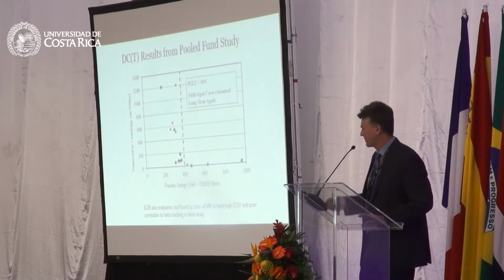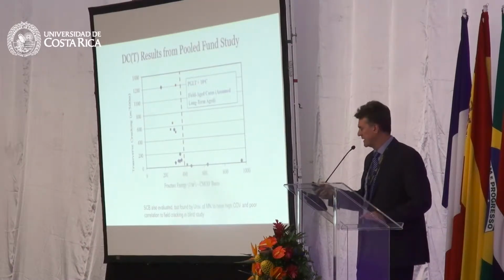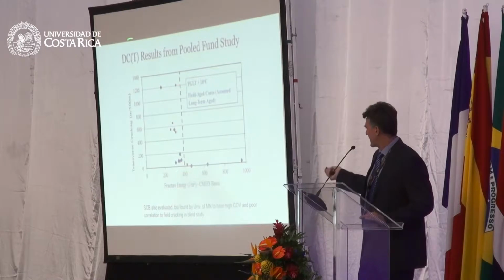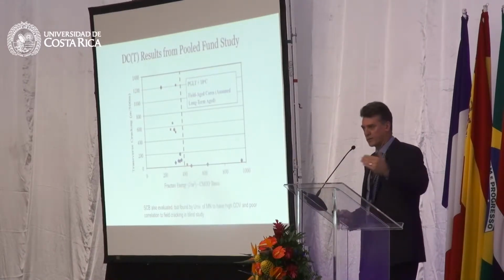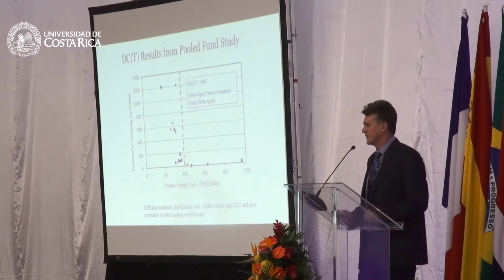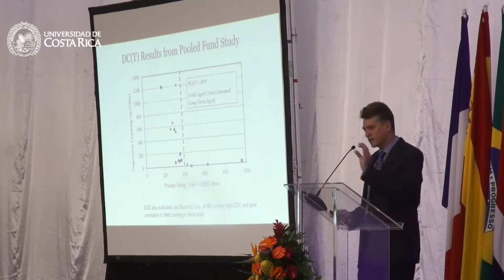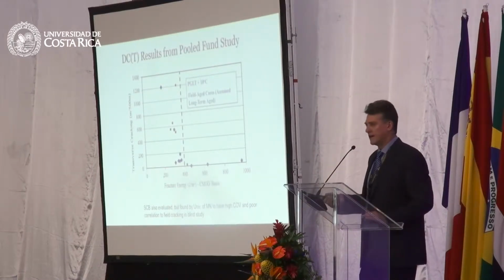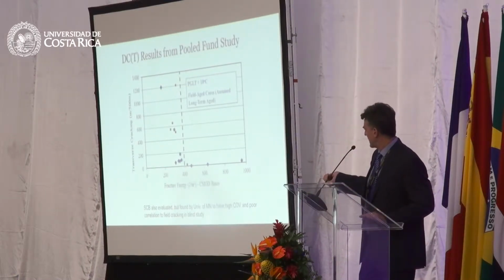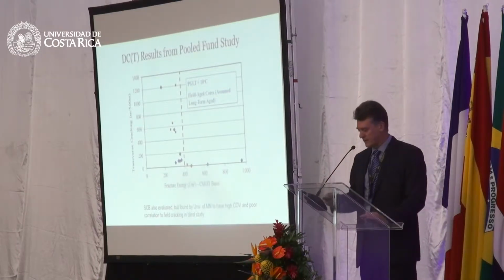We've done many, many more mixtures since this original study, but we definitely saw high cracking on mixtures down below 350, 300 joules per meter squared. So we started to develop specifications where you could get higher reliability by having a higher fracture energy.